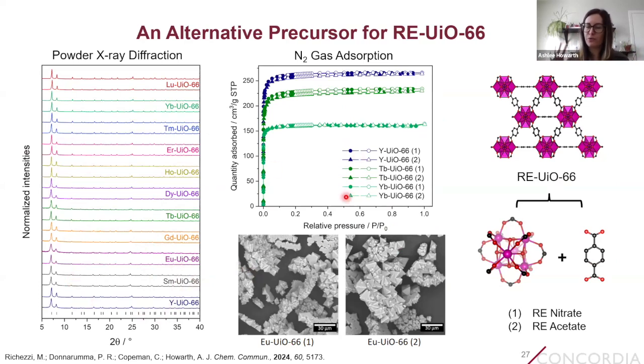We also see that all the porosity and surface areas are the same for MOFs made with the different precursors, but containing the same metal. So here we just have a few examples. You can see the 2 yttrium-based MOFs made with nitrate and acetate, the 2 terbium-based MOFs, and the 2 ytterbium-based MOFs. All have the same nitrogen uptake and BET surface area, whether they're made with the nitrate or acetate. We can also see by scanning electron microscopy that the particle morphology is the same, although we do see some slight differences in sizes depending on the precursor that we use.